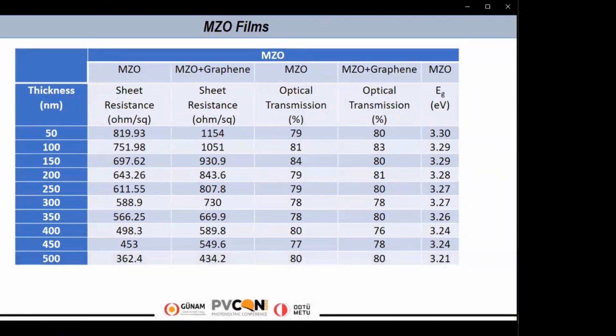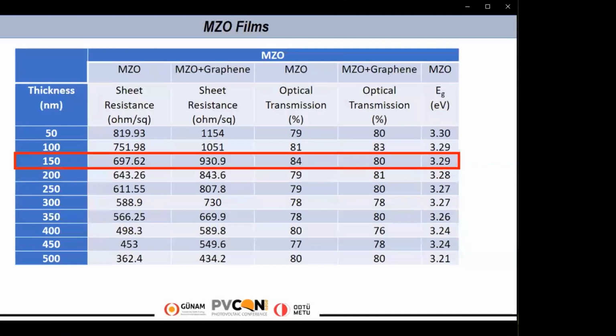When we consider electrical and optical properties of MZO, 150 nanometer films can be the best candidate for the fabrication of solar cells. This situation could be related also, on the other hand, to the MZO graphene hybrid structure, where sheet resistance increased after that. This situation could be related to the high sheet resistance of graphene. Considering only sheet resistance is not enough to determine hybrid structure properties, because graphene has high mobility and high work function. So it can overcome handicaps in the hybrid structure.